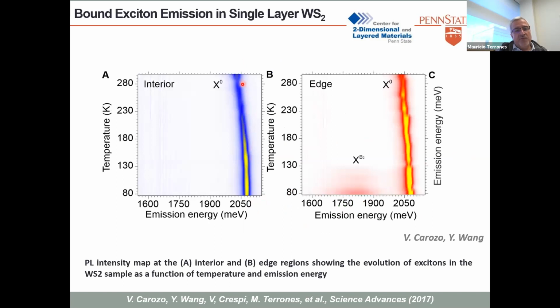When you reduce the temperature, you can see the behavior of the neutral exciton. That means the center of the triangle. And this is the behavior at the edge, where you have the neutral exciton behavior plus the bound exciton. As you reduce the temperature, this bound exciton is more noticeable. This is a thermally activated exciton, right? So you start to see it at low temperature.